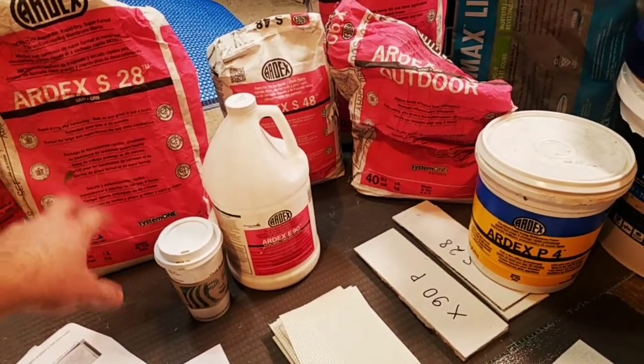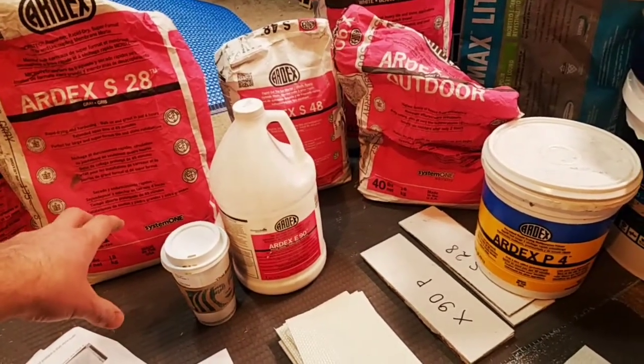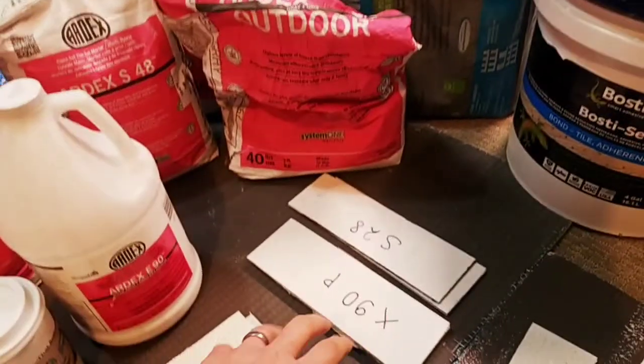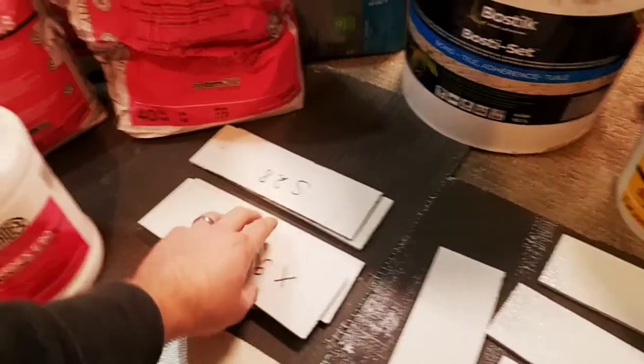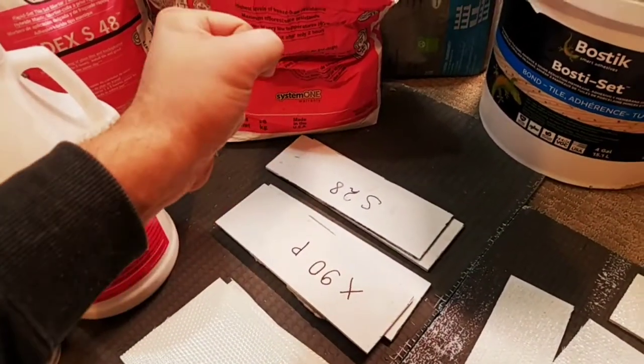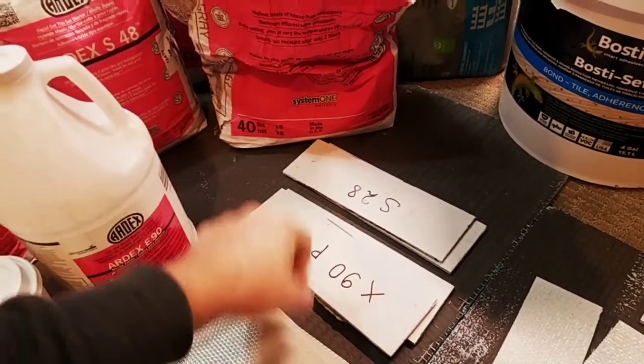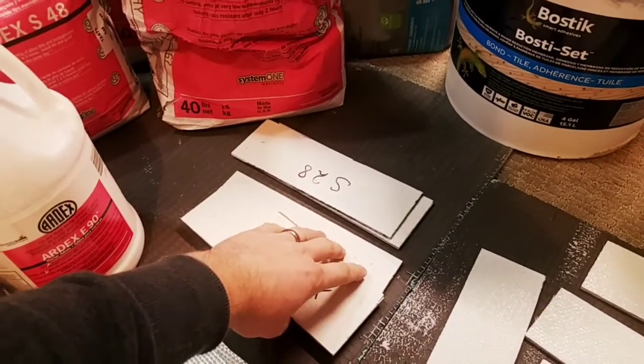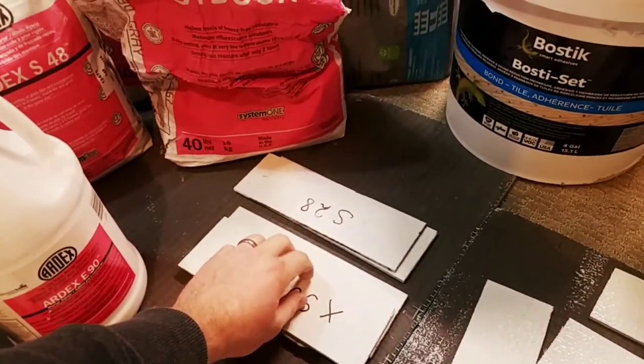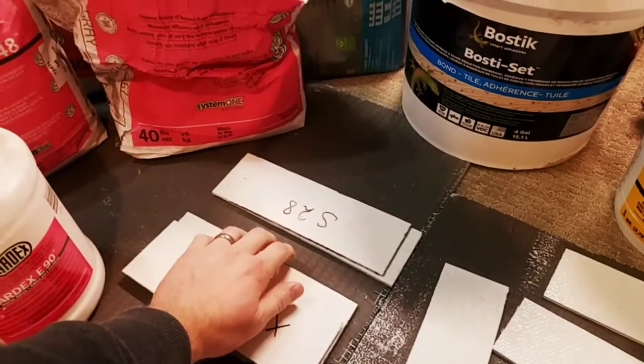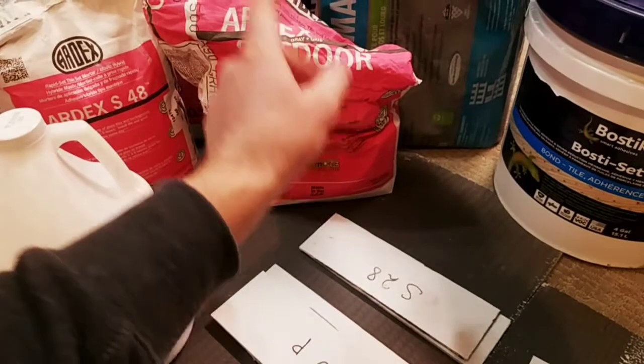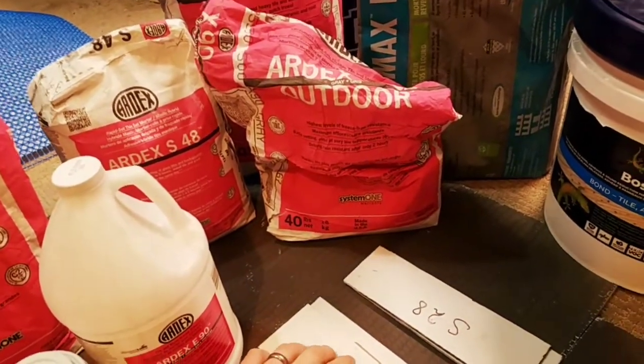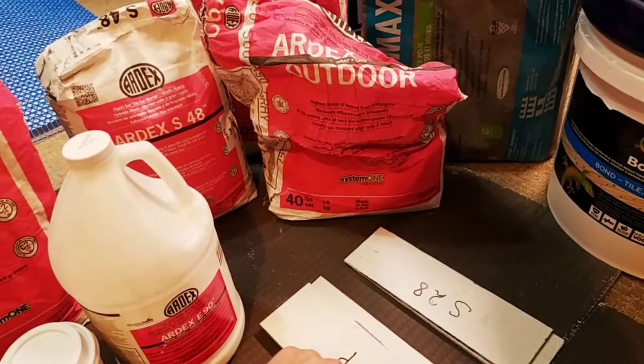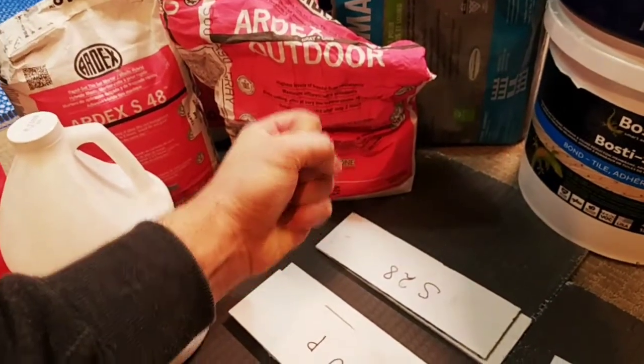Maybe many of you are familiar with our research on marble discoloration in wet areas. If you have more questions about it, just contact me. Also, I want to tell you that about a week and a half ago, I already did a quick test with two Ardex mortars, X90 and S28. Both mortars have tremendous adhesion and bond strength when they dry. They're rapid drying mortars, and I did a 1 day test. I applied S28 and X90 directly to resin backing and removed the tile samples after about 6 hours. Normally, Ardex X90 and S28 dry and are ready for grouting within approximately 4 hours. In 4 hours, they create super adhesion with non-resin backed tiles, and they achieve tremendous strength and hardness.